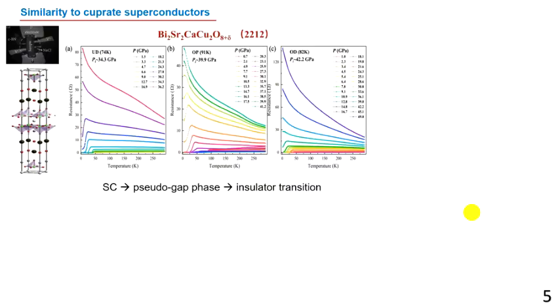Okay, let's now look at similarity of hydrides to cuprate superconductors, and this is 2212 bismuth-based cuprate, where, as we know, there is a border between superconducting state and pseudo-gap phase, and we can cross this border by applying external pressure as it's shown on those three plots. Without pressure, this compound in normal state demonstrates a Fermi-liquid-like behavior. In the normal state, it behaves like a metal, so resistance increases along with increasing temperature. But when we applied pressure and pressurized this compound, we see that the behavior is close to the behavior of semiconductors, because the resistance decreases when we increase temperature.